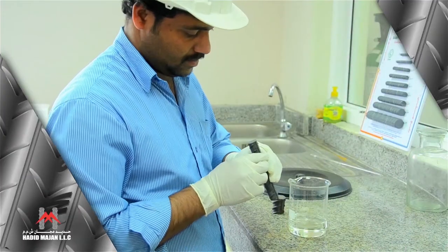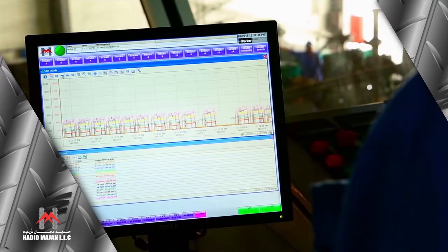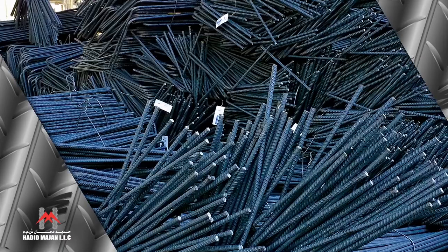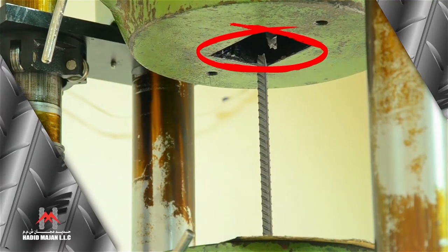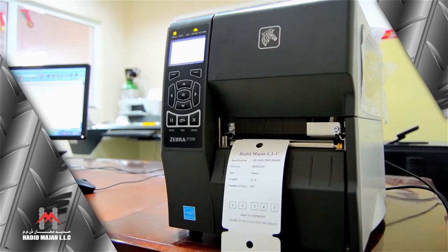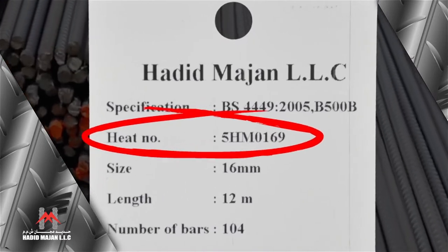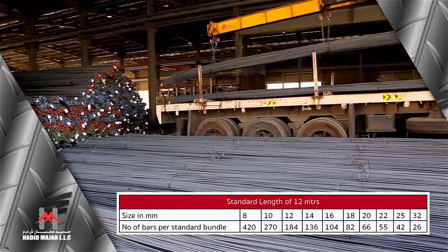The micro-etching test in our lab shows these rings very clearly. Every hour of production, samples are collected by the qualified QC inspectors for routine tests like the tensile test, the chemical test, and the bend and rebend tests. The values are recorded in a traceable manner. The heat number shown on the bundle tags ensures material traceability. Quality approved bars are bundled and kept ready for dispatch.